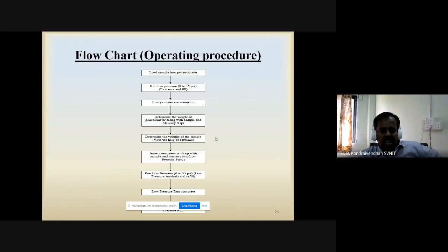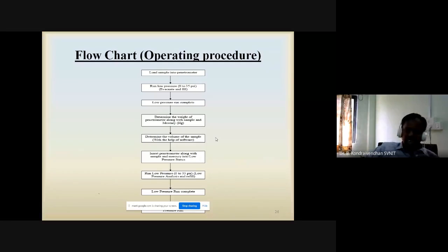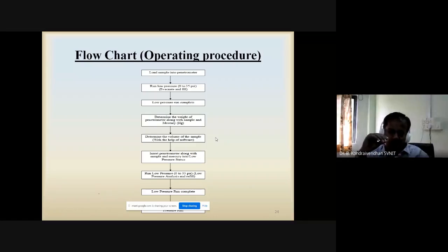Okay. And this is the operating procedure. This is also a very simple procedure, but it used to consume more time. As I mentioned earlier, first you have to do the intrusion side. First you have to do the low pressure station. So first you have to clean the glass cell using isopropyl alcohol, because it is very sensitive to dust also. That's why every time you have to clean the glass cell, and again you have to dry it in the oven.